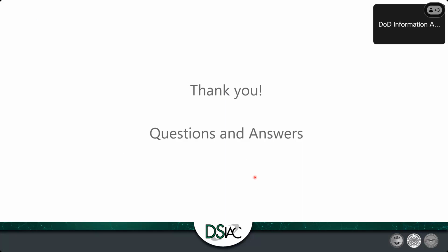Perfect. So first question came in: didn't catch it if you said, but for the mold compression stack, is it also under pressure within a vacuum bag? And then Rob said in the process, the pressure was applied at positive pressure from a hydraulic press, and there was not additional vacuum applied to the material. Yep, that's correct. Then there's a question about defining DIC, digital image correlation, as Rob answered, which uses cameras to track the movement and strains developed in the specimen as it's being tested. Yep.